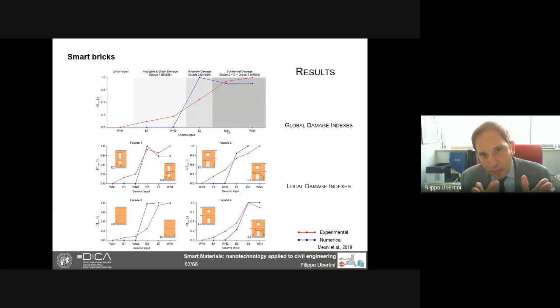So you clearly see that we have an index based on the output of smart bricks that gives us a quite nice ability to track the intensity of the damage. At least we can say yes, there is damage, and yes, the damage has progressed, or no, the damage has not progressed after an earthquake.